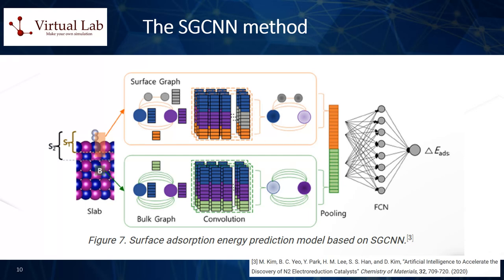The SGCNN is a neural network especially suited for predicting the efficiency of the nitrogen reduction reaction in catalysis, developed under the coordination of Dr. Sang Soo Han and Dr. Donghun Kim of the Korea Institute of Science and Technology. While CGCNN predicts bulk properties of materials very well, a disadvantage appears when considering surface properties, which are harder to predict. A novel graph-convolutional neural network of slab structures was specifically developed, making it possible to predict the adsorption energy on the surface of a candidate catalyst material by entering only the characteristics and connectivity information of its constituent elements. This SGCNN approach proved flexible enough to be extended to other reactions beyond the nitrogen reduction reaction.